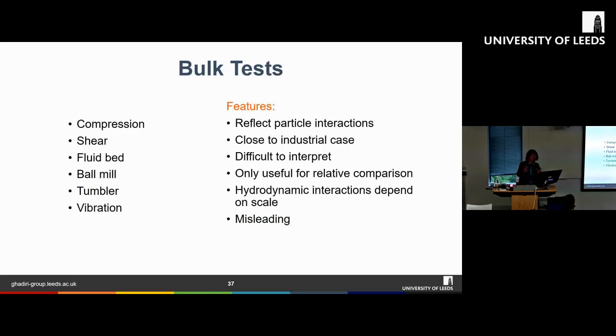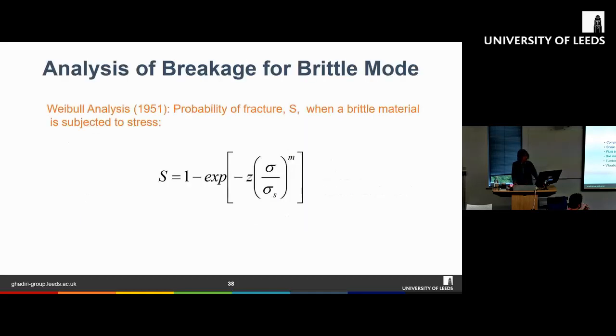For example, looking at compression of a bed of particles. Here are some examples of different bulk tests: shear, fluid bed, ball milling, tumbling, and vibrations. The feature of bulk tests is that they do reflect particle interaction, because we're talking about bulk particles where the particles get to interact against each other, and they are closer to industrial cases. But the problem with bulk tests is that they are sometimes quite difficult to interpret, and they're useful for relative comparison. But if you're not careful, you can give very misleading interpretations of the data that you get.